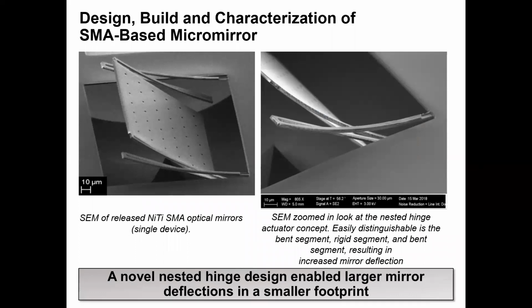So these SEMs here were taken on fabricated and released SMA MEMS micromirror devices. The actuator arm was designed to have alternating segments of bent, rigid, and bent beams, and this was to impart more overall curvature in the beam and a larger deflection in the micromirror. So these beam segments were comprised of active SMA, which could undergo the shape memory effect to drive the micromirror. The rigid segments were comprised of a thicker photoresist, in order to just limit bending in those regions. And the key takeaway here is that this novel nested hinge design enabled larger mirror deflections in a smaller footprint, which is more suitable for tightly packed mirror pixels.